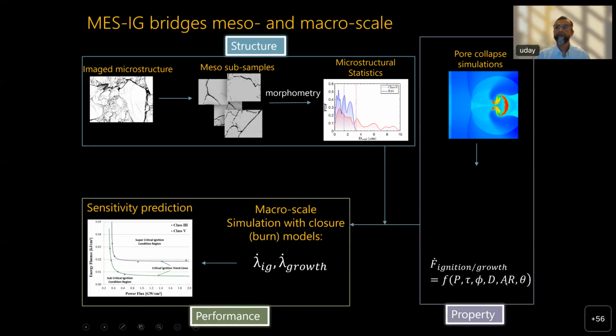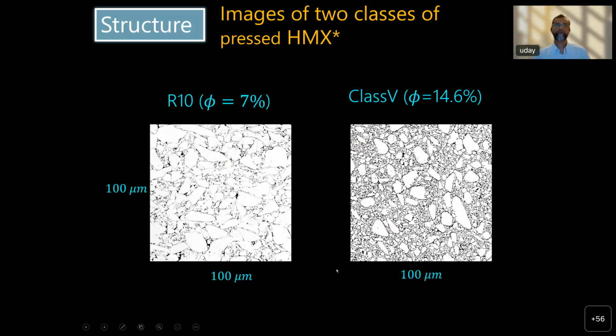And what we do is we get this hypersurface, or a surrogate model, for the ignition and growth rates of these single pores as a function of the shock pressure, the shock pulse width, the porosity, the diameter of the voids, or the size and shape of the voids. These three parameters are size and shape of the voids. And then we get a surrogate model, and then the surrogate model is used to close the macro scale simulation. So that's MES-IG.